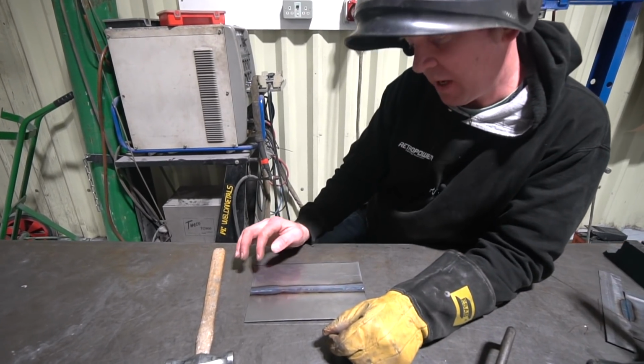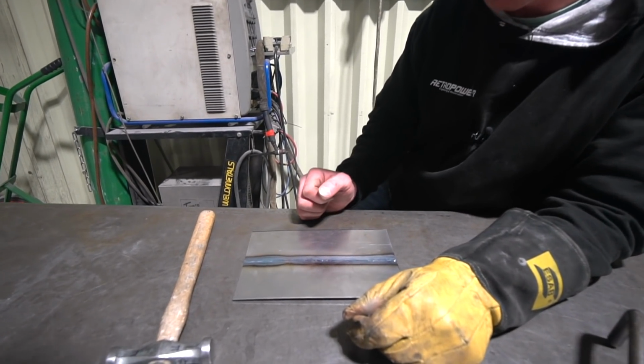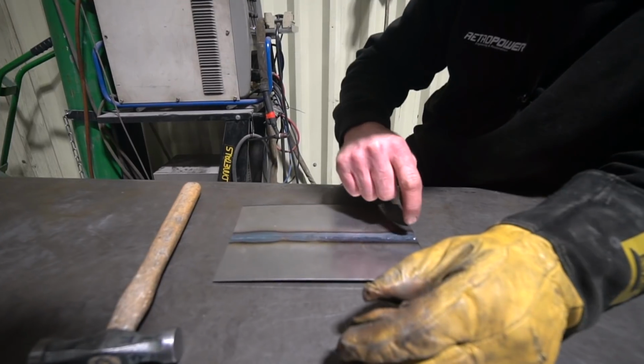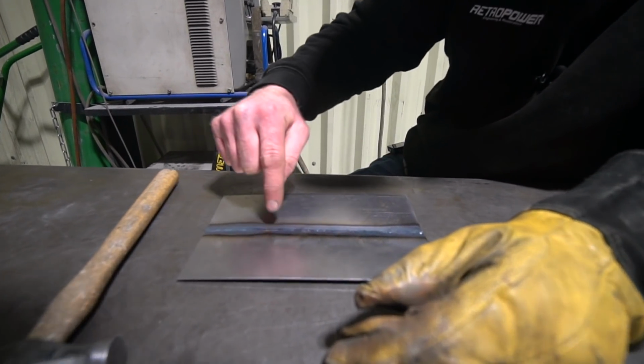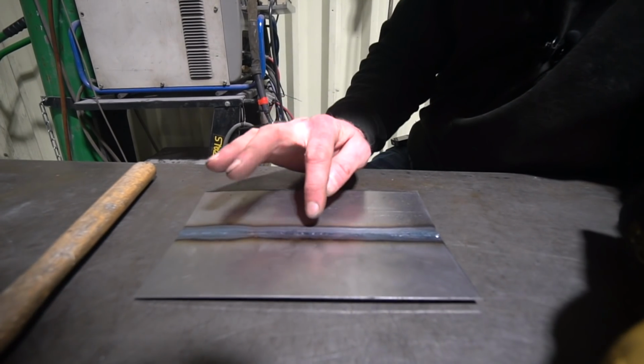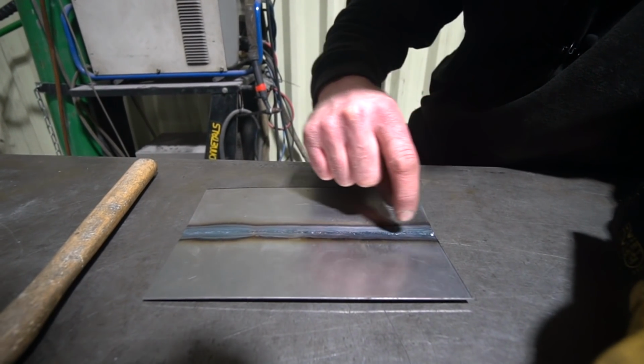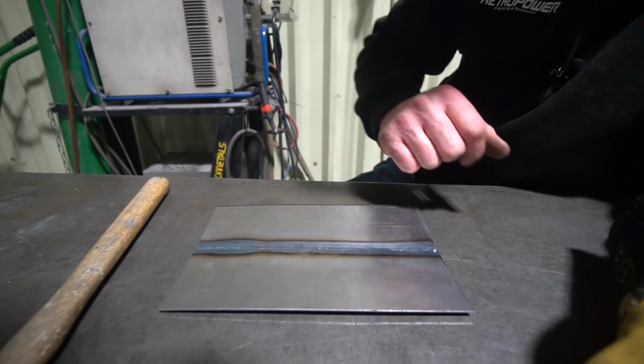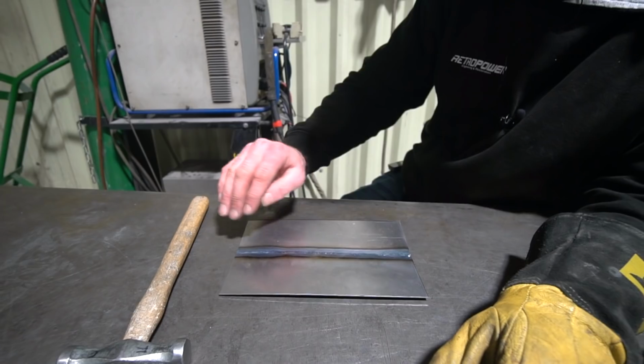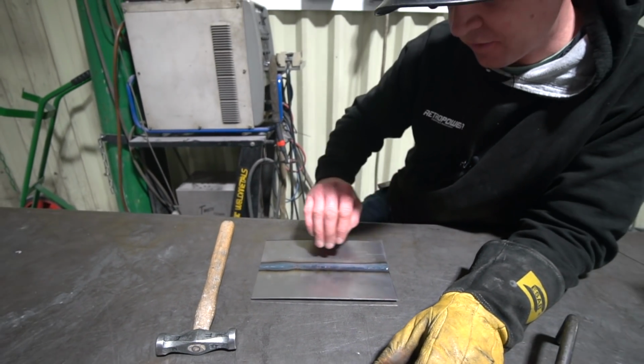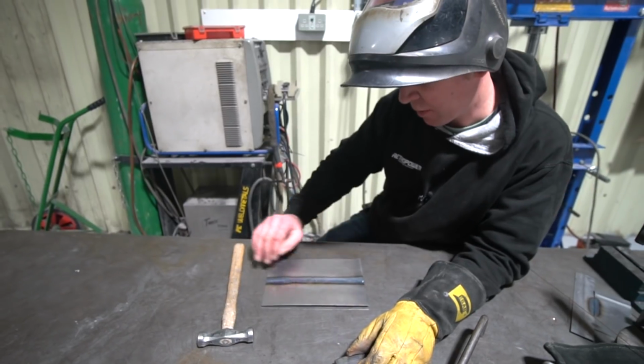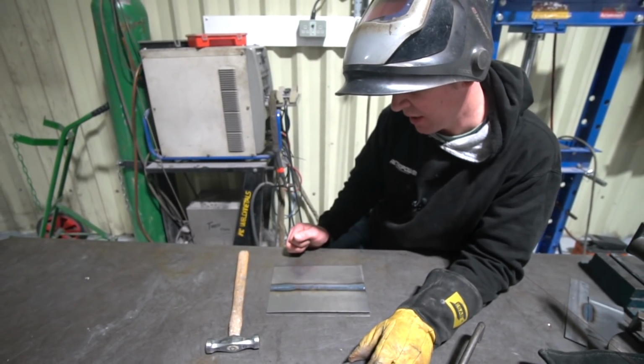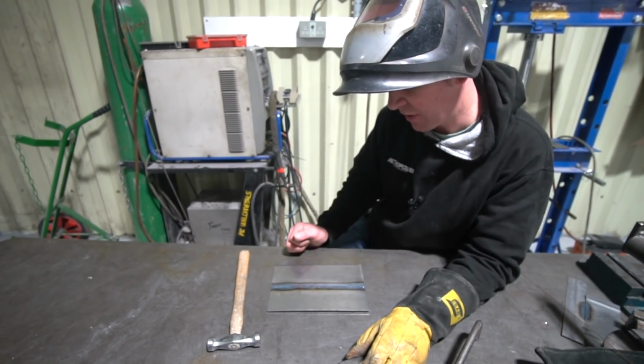And the key bit for knowing whether you're going to be able to planish the panel up nicely afterwards is if that heat affected band is nice and even. Now I've got a dip there, a little bit of a dip there, but it's not too bad. If that heat affected band is nice and parallel, the chances are that you've applied the same heat all the way along, you've put the same amount of filler rod in all the way along, and you should be able to planish that out really quite nicely and make a neat job of the finished panel joint.